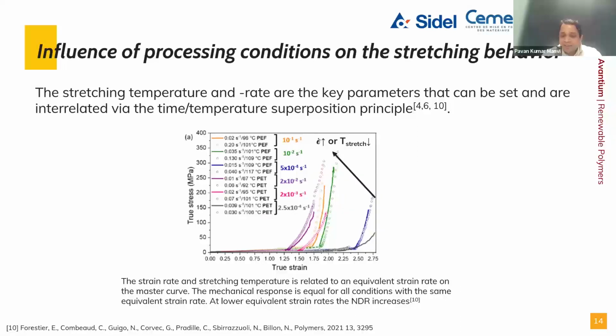So these are the effects that we have to correlate with the melt spinning process. When we decide on a different kind of spin pack hole diameter and a different L to D ratio, then how much shear rate can be imparted, what kind of nucleation or strain induced crystallization we can expect, and how the filament properties will result thereof. So this information is always necessary to keep in mind when setting up the melt spinning process. If we go into the detail of the individual curves, it will take a very long time, but I just wanted to give some overview of how the temperature and the shear rate can affect the properties. If there are any questions, definitely we can talk in the Q&A session.